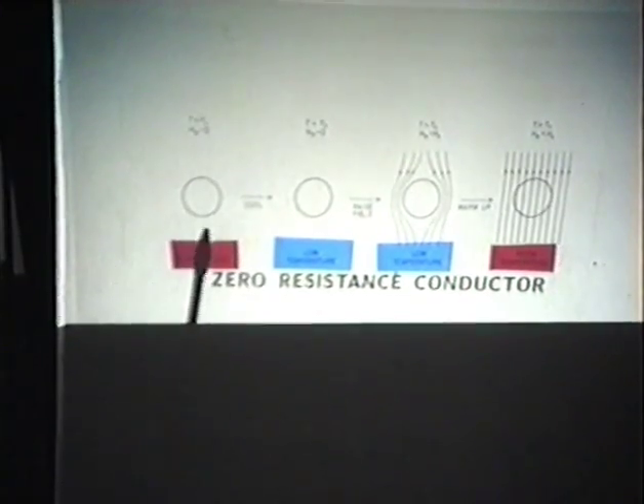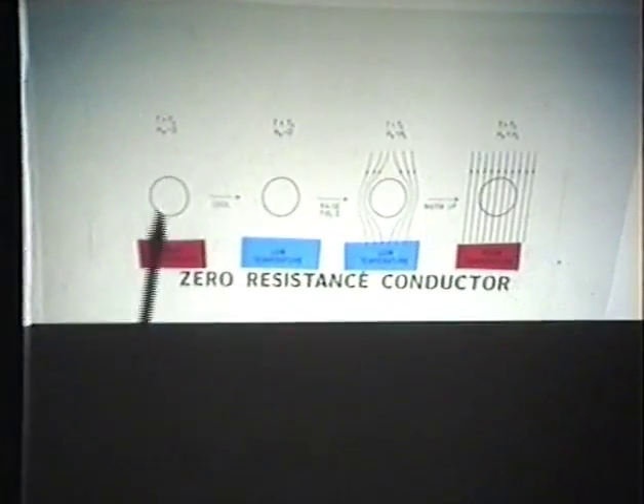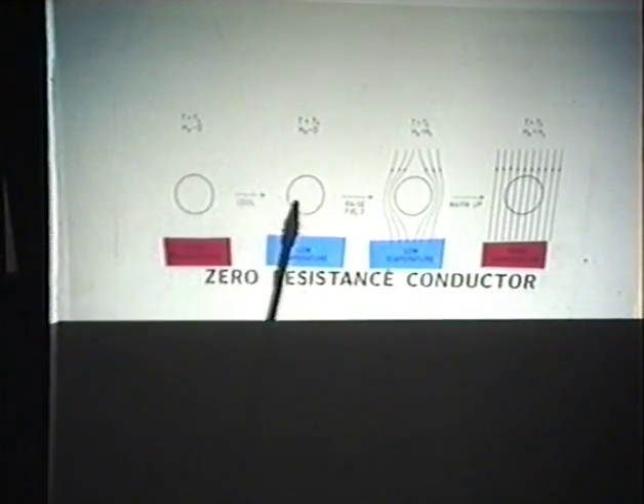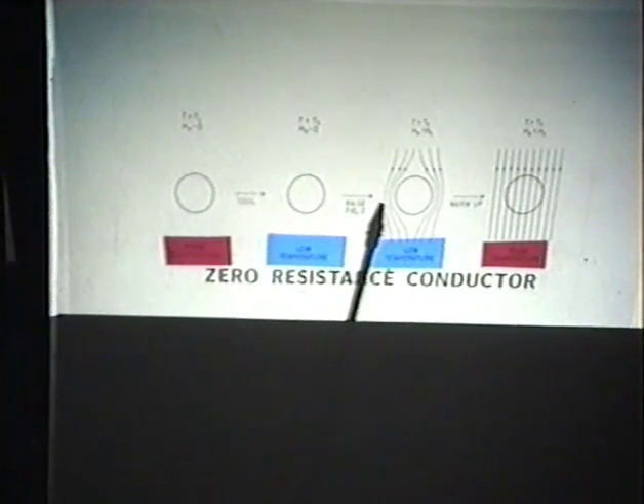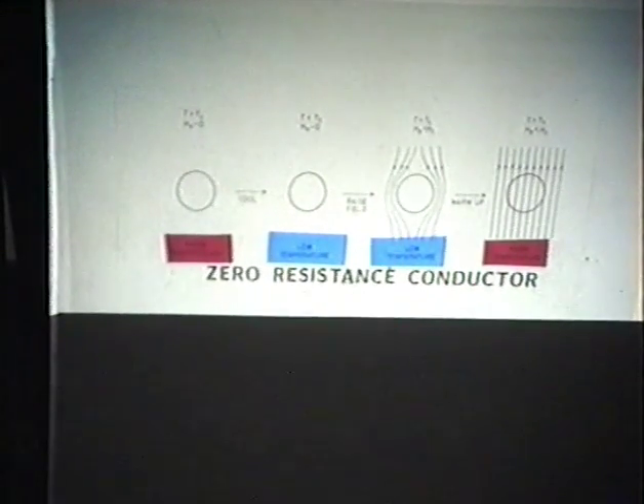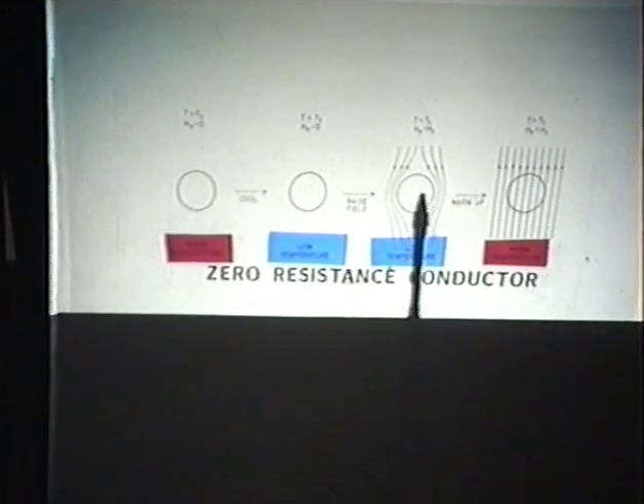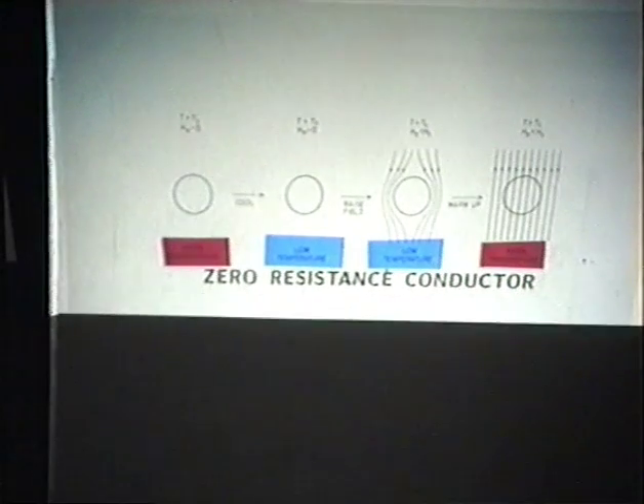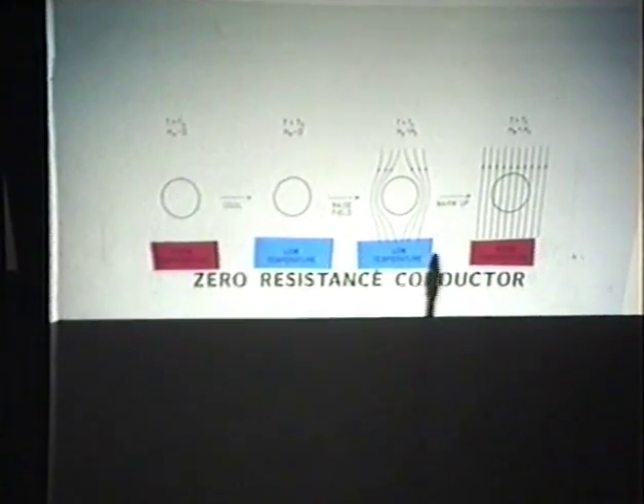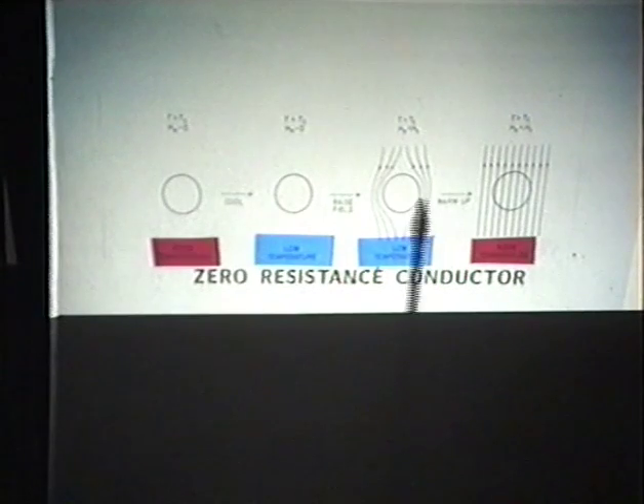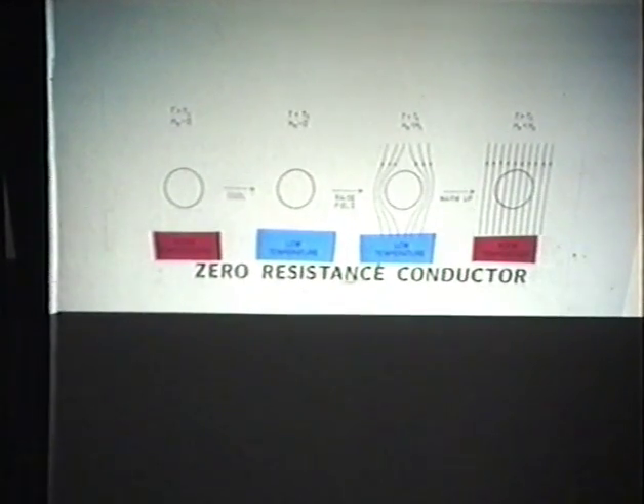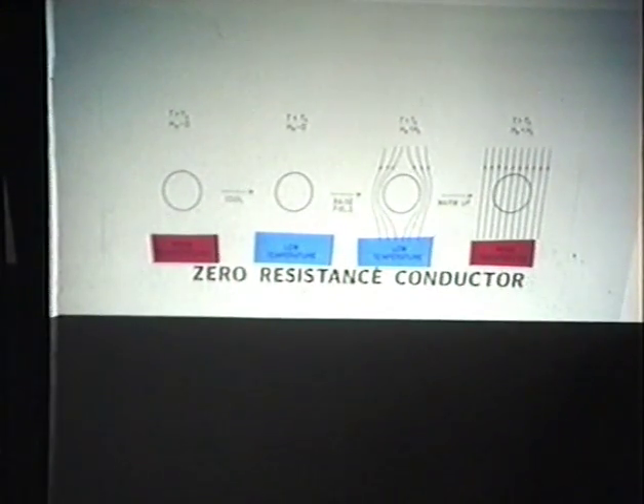Okay, so we can imagine a little experiment here where we start with a lump of this stuff at room temperature, you cool it down so it turns into a superconductor, and then you raise some kind of external magnetic field, and because the changing magnetic flux generates eddy currents, the external field is kept out of the body of the superconductor. And then if you kept the external field on and you warmed up the superconductor, you would then find, of course, it returned to its normal state and the field was able to permeate it once more because the eddy currents died away.